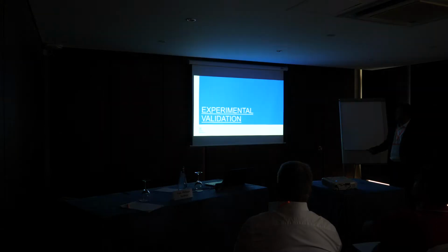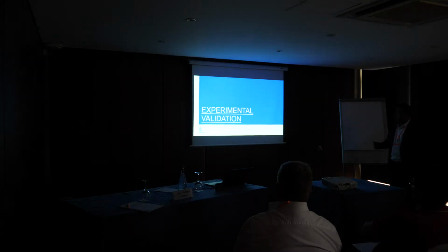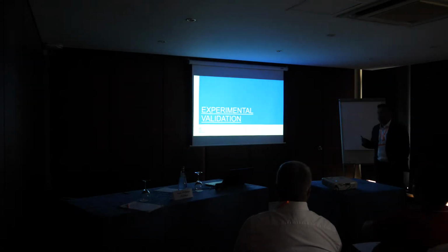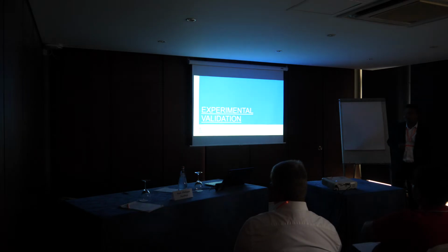for AMW ratios from 0.05 to 0.1. We also modified the compliance value over here, and this is the standard test, standard geometry for 4-point bending in the base standard. To validate the numerical values with the experimental results, in the end, because we have to calculate the crack growth for the welded specimens,